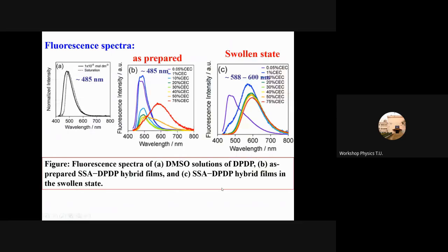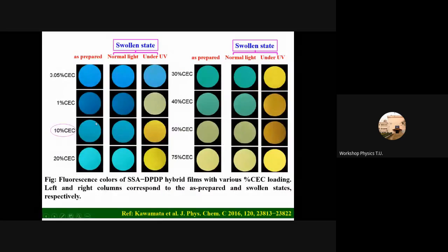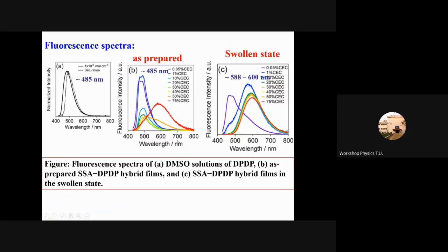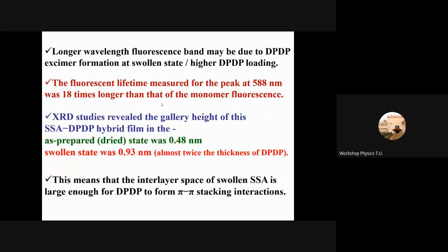So we tried to understand why this happened. I'm not explaining all these kinds of things. We did some spectroscopy to have an idea why this happened. We have seen that the spectral features of the SSA-DPDP film and the swollen film, that is, after putting the solvent, are quite different. And in fluorescence, the swollen film showed a longer wavelength, broad structureless band. And this is mainly due to excimer. Excimer means some kind of aggregation. One excited state molecule and one ground state molecule overlap each other, and they form some kind of aggregate. Accordingly, their spectroscopic behavior changes.